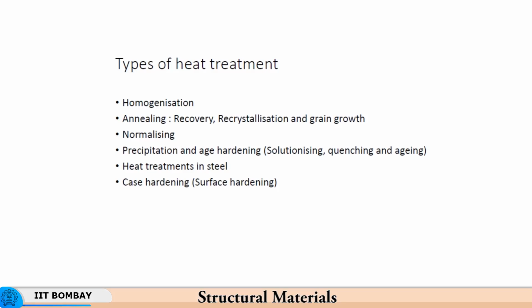So, annealing is done with three purposes. One is to just dissipate the internal stresses by causing local plastic deformations. Then you have recrystallization taking place, meaning the old grains are replaced by the newer ones, and then the grain growth takes place. You do not want the grains to grow indefinitely. So, you do not want, let us say, too fine grains, you do not want too coarse grains. So, the grain size that you want can be adjusted during the annealing process.